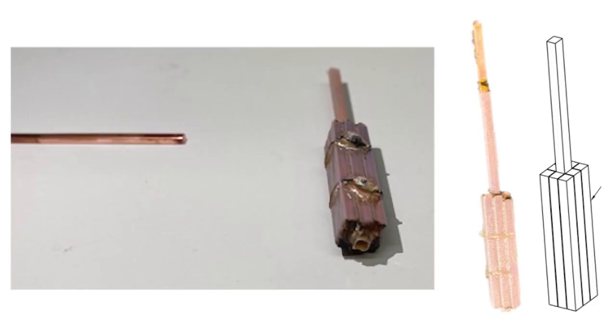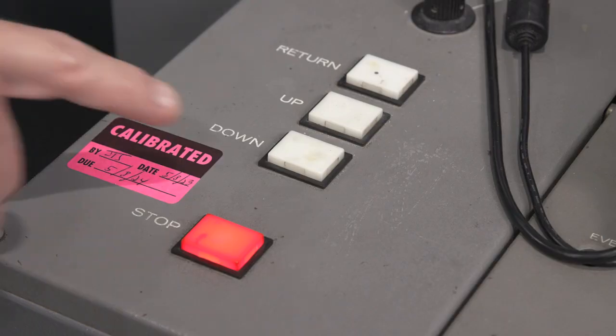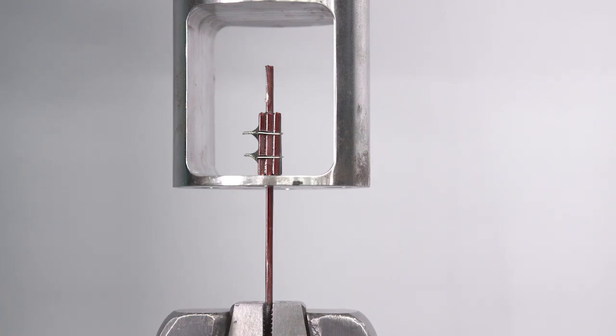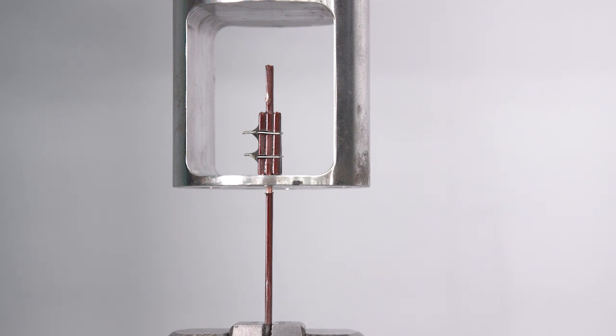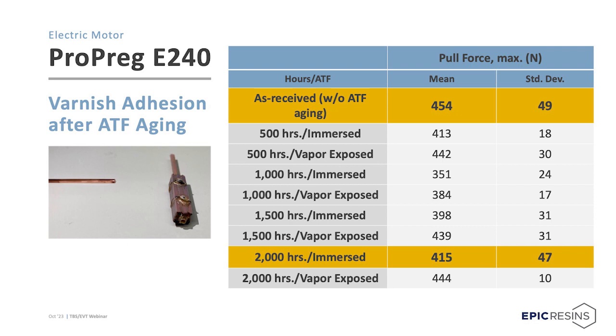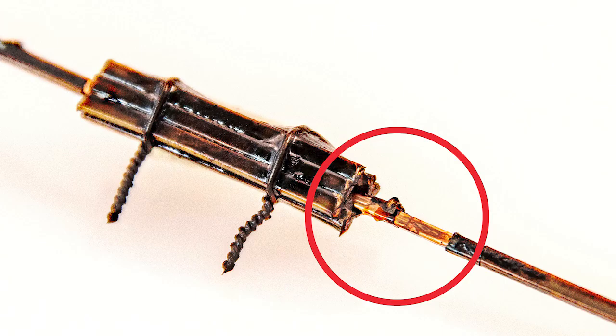Samples are then conditioned for a total time interval of 2,000 hours. The integrity of the adhesion is then tested by the fixture in this illustration. This fixture measures the force required to break the center wire free, which mimics the wire in the slot. From the data collected, you can see that after 2,000 hours at 150 C exposure immersed in ATF, over 91% of the original adhesion is maintained, and over 97% maintained for ATF vapor exposure.